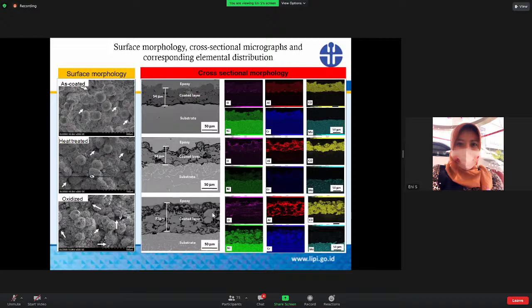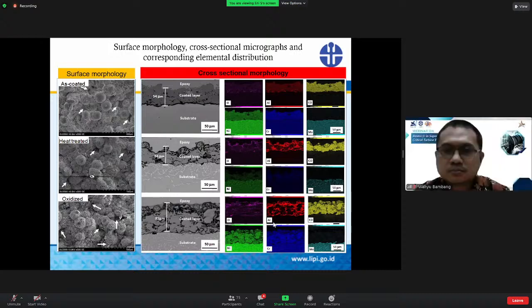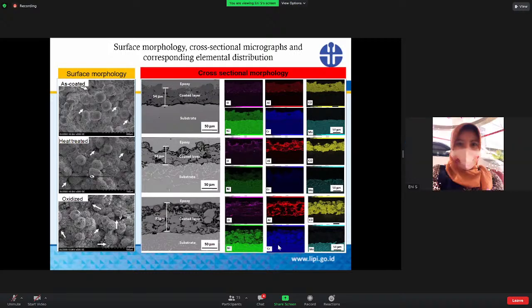The intensity of the oxygen on the top layer reacted with the aluminum, cobalt, nickel, and chromium elements. Therefore, it may cause the formation of transition alumina phases with a complex structure from the initial stage up to 100 hours at 1000 degrees C.